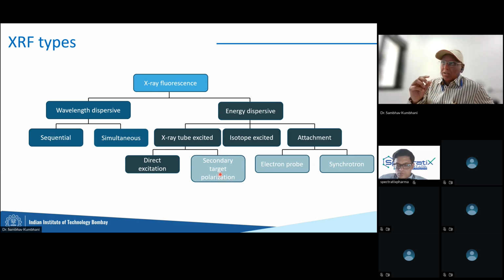It means an X-ray hits some very specific material. These are known as polarizable materials, and then the X-ray gets polarized because of it, and that polarized light then hits the sample, which causes the excitation. So when I say multiple electrons can be removed at a time, then it becomes confusing to find which element it is. So to control that, we sometimes use polarized light, and that will ensure only one electron is removed all the time. So that's still direct excitation in a way. Then sometimes isotopes are used. So these are radioactive material. They have enough energy in them to knock off electrons as well. So that is one way to do it.